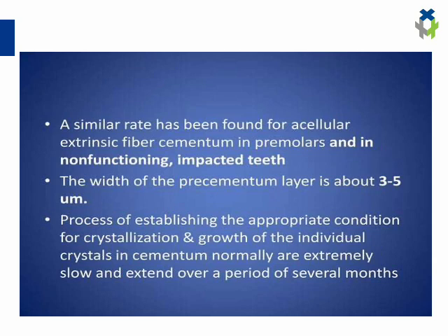A similar rate has been found for acellular extrinsic fiber cementum in premolars and in non-functioning impacted teeth. The width of the pre-cementum layer is approximately 3 to 5 micrometers. The process of establishing the appropriate conditions for crystallization and growth of individual crystals in cementum is normally extremely slow and extends over a period of several months.